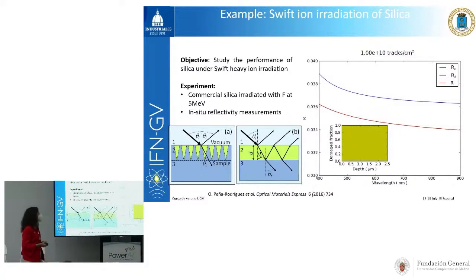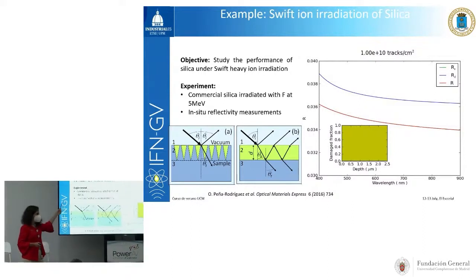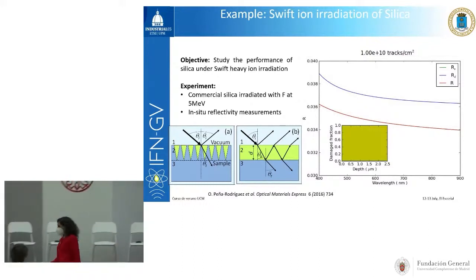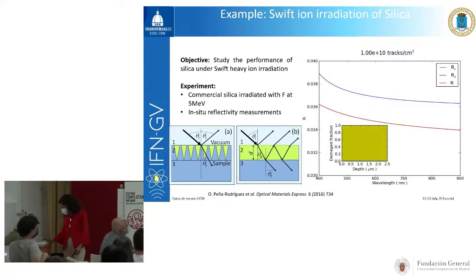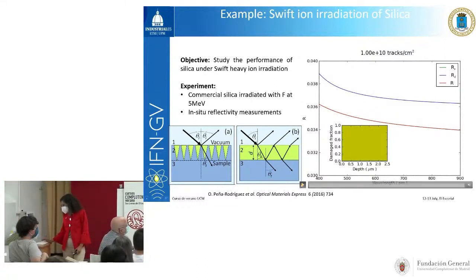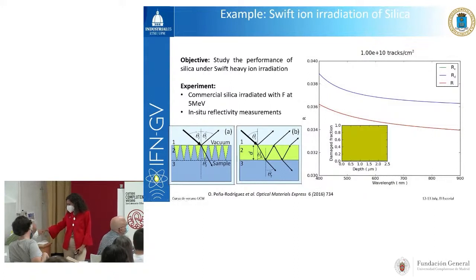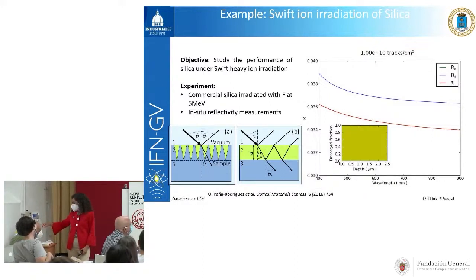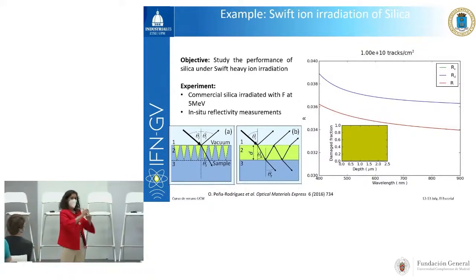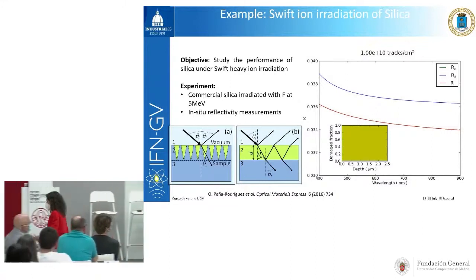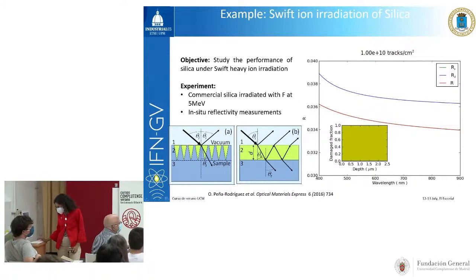Basically, the objective was to study the performance of silica under swift heavy ion irradiation. They were irradiating silica with fluorine at 5 MeV, with high energy. And then they were carrying out in situ experiments, and this is the video you may see here. You see the reflectance of the sample against the wavelength, and you may see the changes between the red and the blue curve when increasing the radiation fluence. So basically, this is what you are going to see in the video.